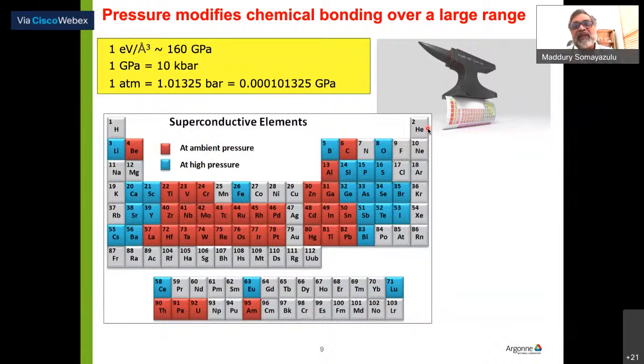Pressure begins to put an enormous amount of energy into your system. And in fact, if you talk about 1 eV per angstrom cube, you're beginning to talk about situations where you are pushing two atoms closer than what they would be in the closest approach in a van der Waals curve. So already you're beginning to tune the bonding between elements. And so that is signified here. In other words, you can say that pressure changes the periodic table. I mean, that's what this cartoon here says, that pressure completely modifies the periodic table.